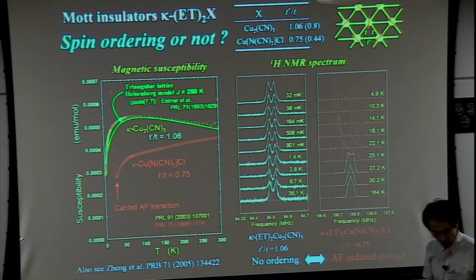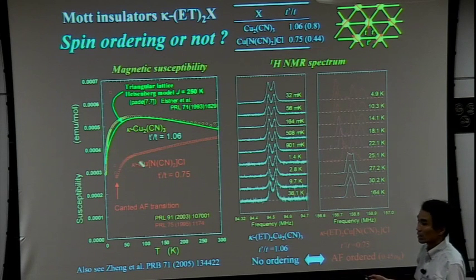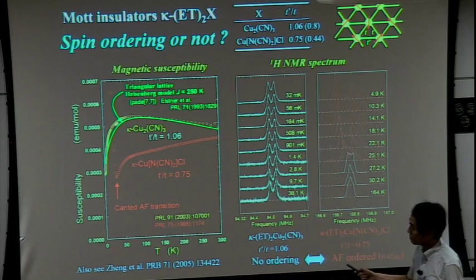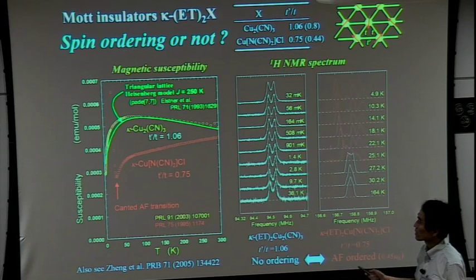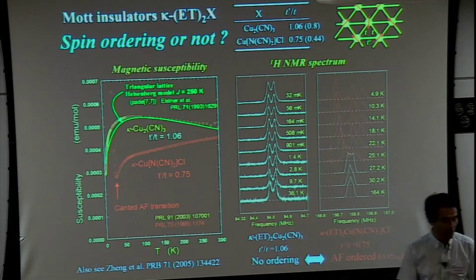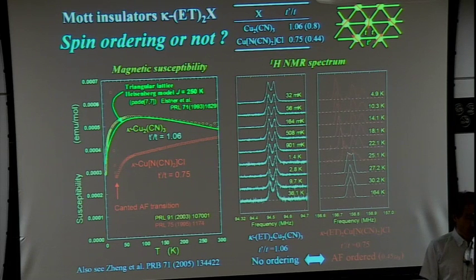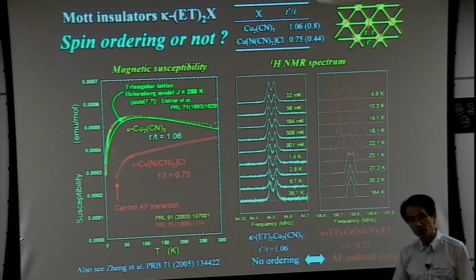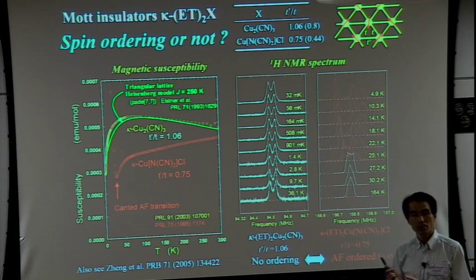I'd like to remind you of one significant point: the temperature dependence of the magnetic susceptibility is well reproduced by the triangular lattice Heisenberg model. This is very important, I think, because the triangular lattice Heisenberg model gives a ground state of the 120-degree Néel state. However, the real ground state is a spin liquid.